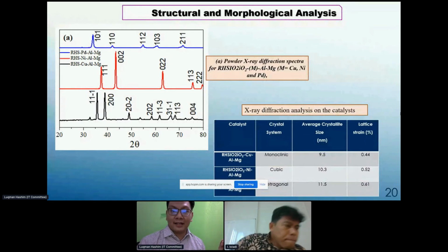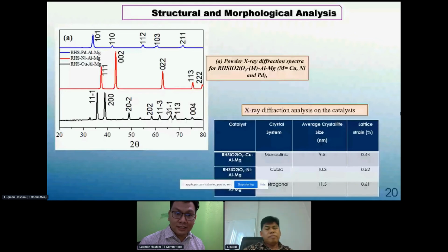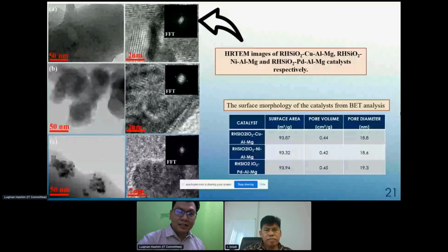And basically for XRD, the main point I want to draw to you is that there is not much difference in the catalyst systems for them to be too different from one another, which makes sense since they are synthesized via the same process at the same parameters. However, as you can see, lattice strain and average crystallite size have an increasing trend from copper to nickel and palladium. However, no actual collapse of the structure took place, as we shall see here. They are actually similar. The lattices are similar in the HRTEM images, which again, as I say, makes sense since they are similar in production.